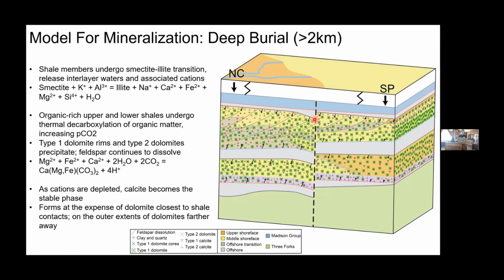So during this time, again, we're about 100 degrees C. The shale members undergo the smectite to illite transition, which releases interlayer waters and associated cations. This equation here shows what that looks like, but it all depends on the composition of the initial smectite, which of course we don't know. But generally, this reaction releases a lot of calcium, iron, and magnesium, aka the ions that would be present in those ferroan dolomite rims that I mentioned.